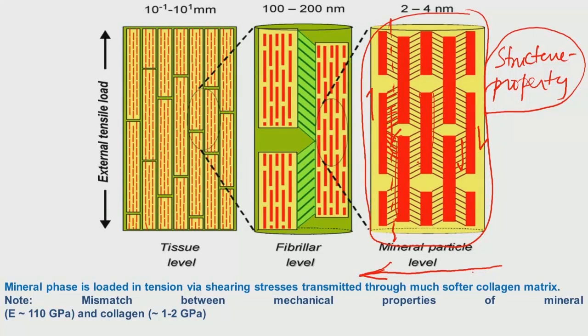So this is at the mineral particle level, the 2 to 4 nanometer level, this is the description. But then, for the individual collagen bundles at the fibrillar level, several of these collagen fibrils are present. Again, between these fibrils, you have this kind of weaker bond structure. And then if you go to the tissue level description, this is a small region of the tissue which is magnified here, and this small level of fibrillar description is being magnified here.